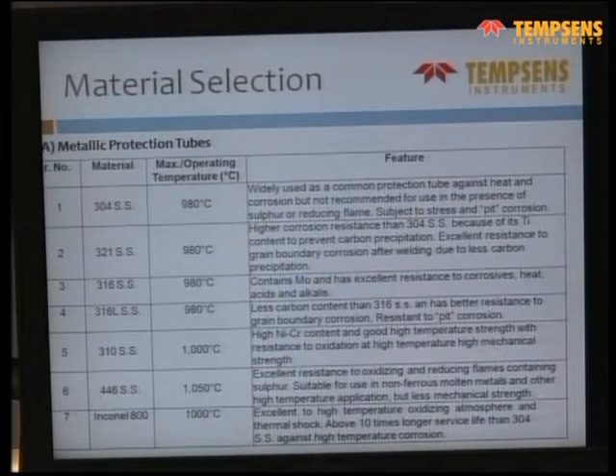For example, 446 and 310 both have a similar temperature range, and even Inconel 800, you can see it is about 1000, 1050, or again 1000 degrees centigrade. But 446 is more used, it has better life in case of sulfuric atmosphere, or in case of a non-ferrous molten metal. So 446 is a chosen material in a cement plant or a molten aluminum plant, or primary aluminum plant, where they want to take the temperature of molten aluminum. So according to the chemical as well as the temperature, you have to choose the right material of the thermowell.